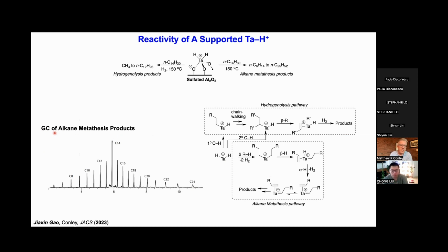So the GC of a typical alkane metathesis reaction using our catalyst here, this is what we observe. We can assign all of these as the linear alkane. The branched alkanes, we do generate little bits, but not much. If you compare that to the neutral tantalum hydride on silica, you get significantly more branching in your GC traces, suggesting that there could be a difference in selectivity for the sigma bond metathesis reaction.